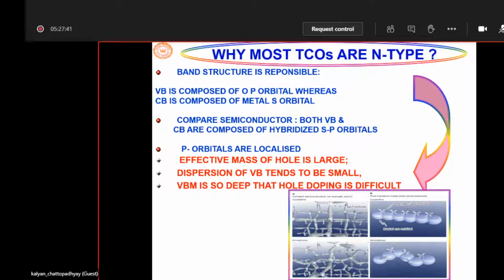Now, you know that in these transparent conducting oxides, the valence band is composed of oxygen p orbital. If you look at this cartoon, you can see that these are the p lobes, and these actually constitute the valence band. On the other hand, the conduction band is composed of the metal s orbital, which has larger volume and is spherically symmetric. So suppose somehow you generate electrons by, say, a donor level, then the electrons can move very easily at some small electric field within this very large space of the conduction band. So N-type doping is not a problem.